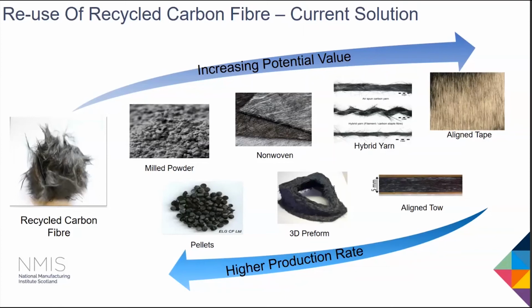So the researchers started to think about realigning the fibers. You can see the hybrid yarns, which can be manufactured by a traditional textile process called the friction spinning process. The format of this material is very similar to the virgin fiber products. But because the fibers are only partially aligned and there are some issues of fiber attaching, the mechanical property is not very good, and you need to spend extra cost on a secondary conversion process to convert the yarns to fabric or preforms, through braiding or weaving.